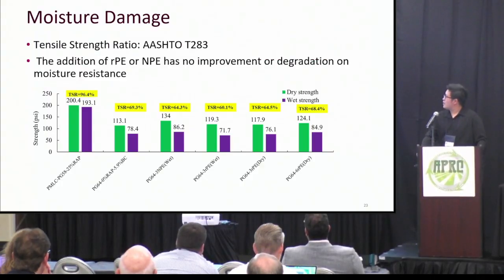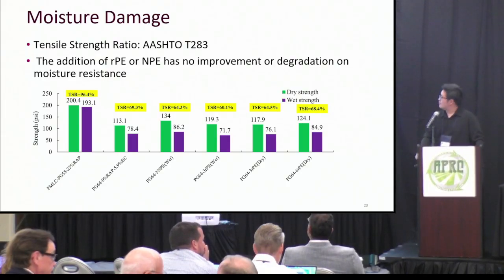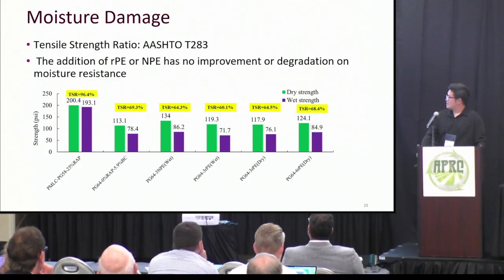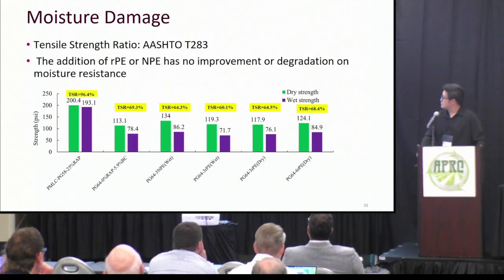And also we ran the tensile strength ratio test. It's for moisture damage. So very interesting: the addition of recycled PE mulch or new PE mulch has no improvement or degradation on moisture resistance.